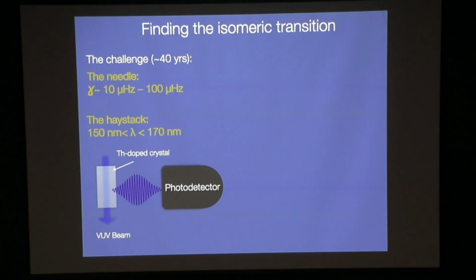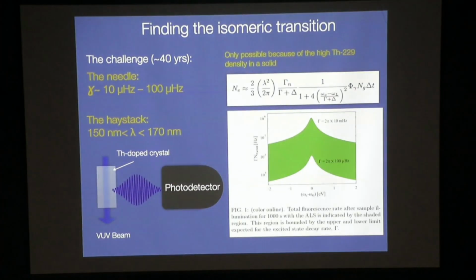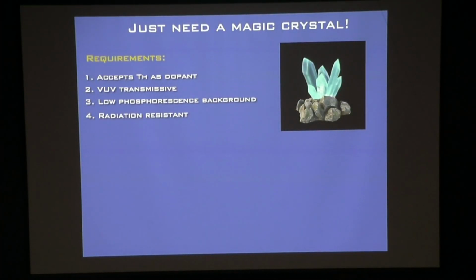And that's exactly what we set off to do. Because using, say, the Advanced Light Source, we could scan this 140 to 180 nanometer range in a couple of days. Whereas if we had to do it with a laser, it would take a few years. And so we set off to do this at the ALS. The problem, and this is why it took so long,